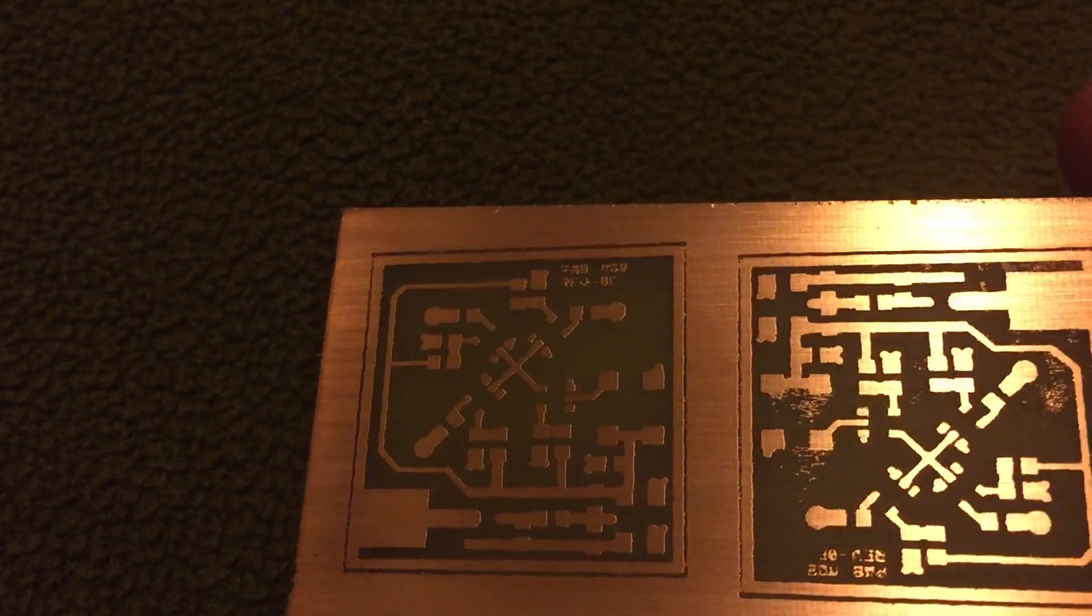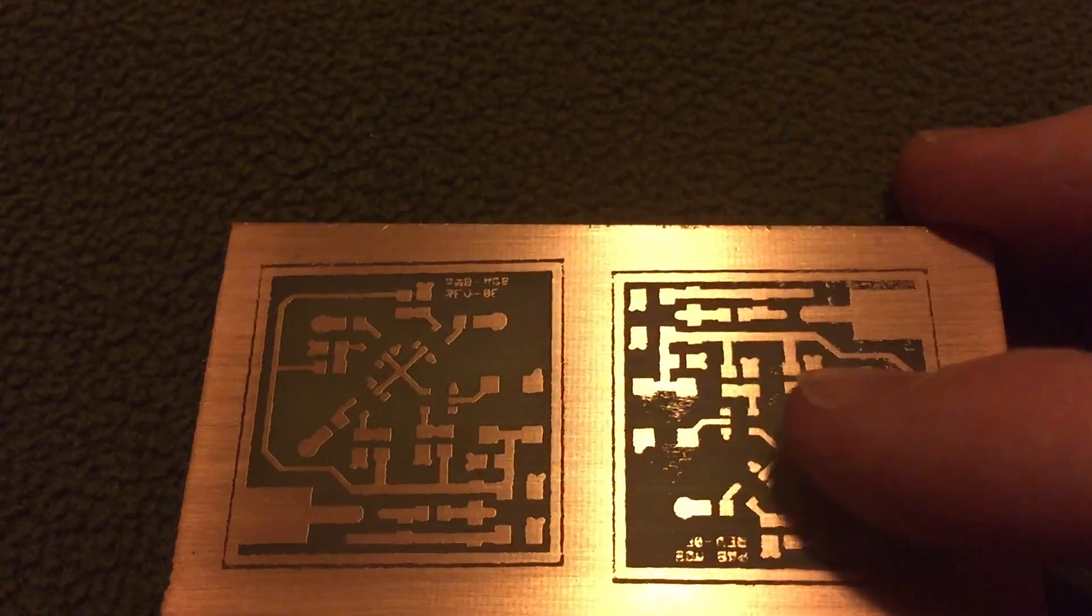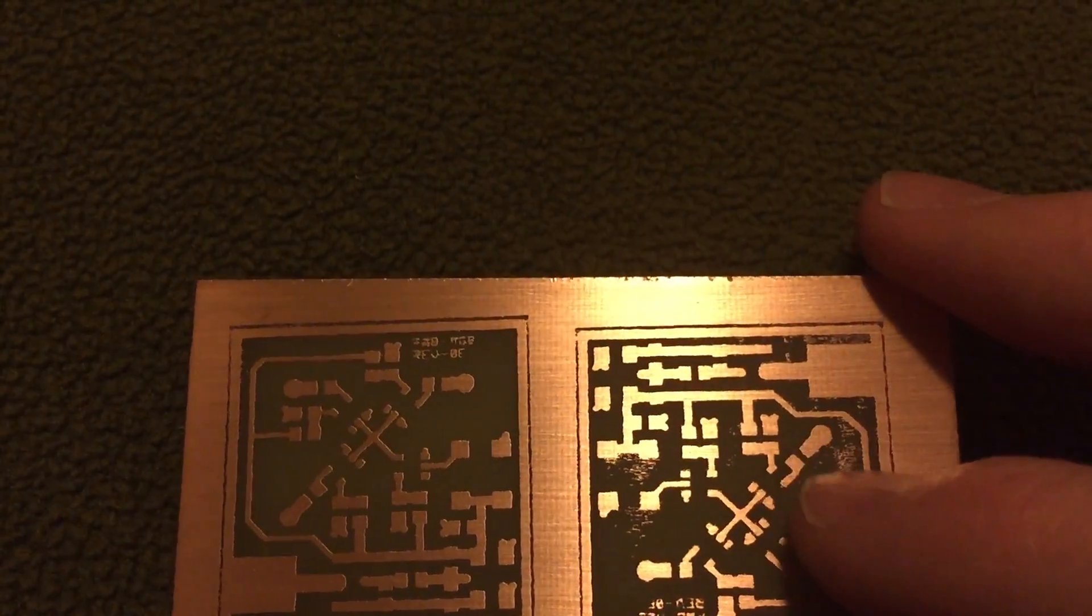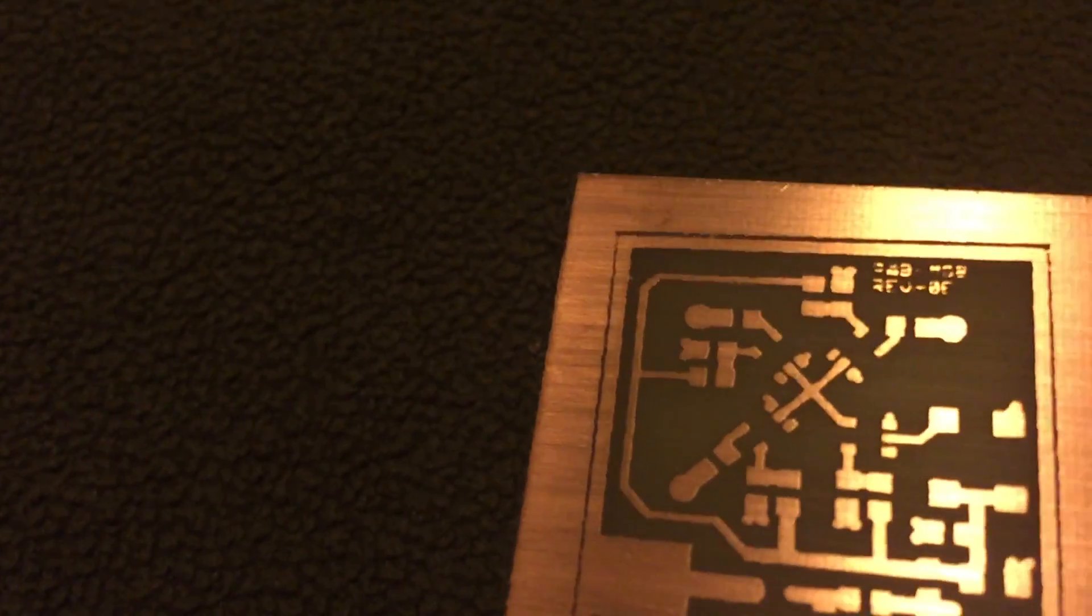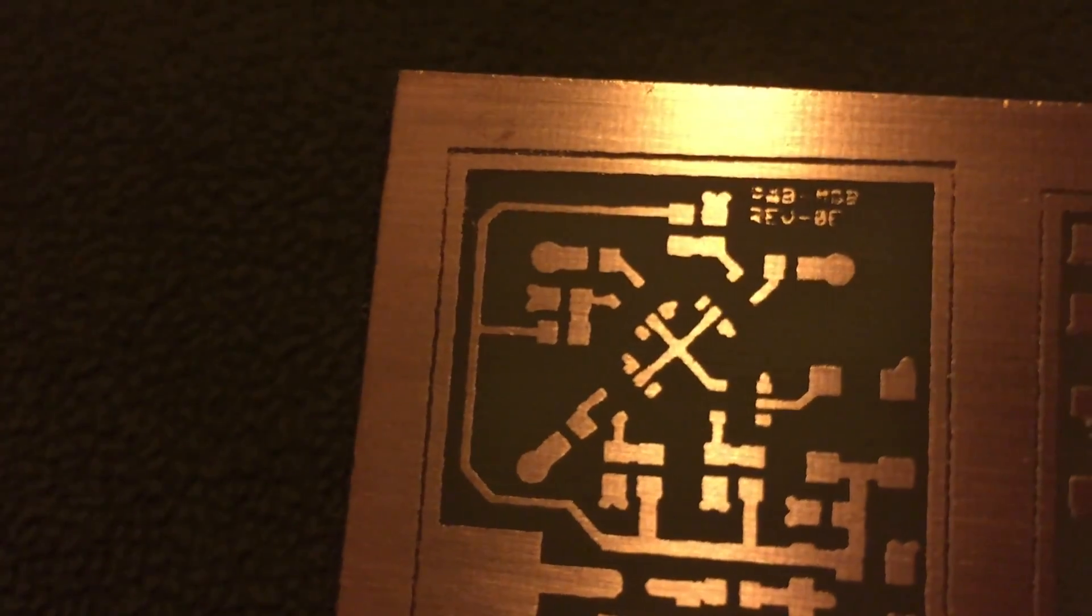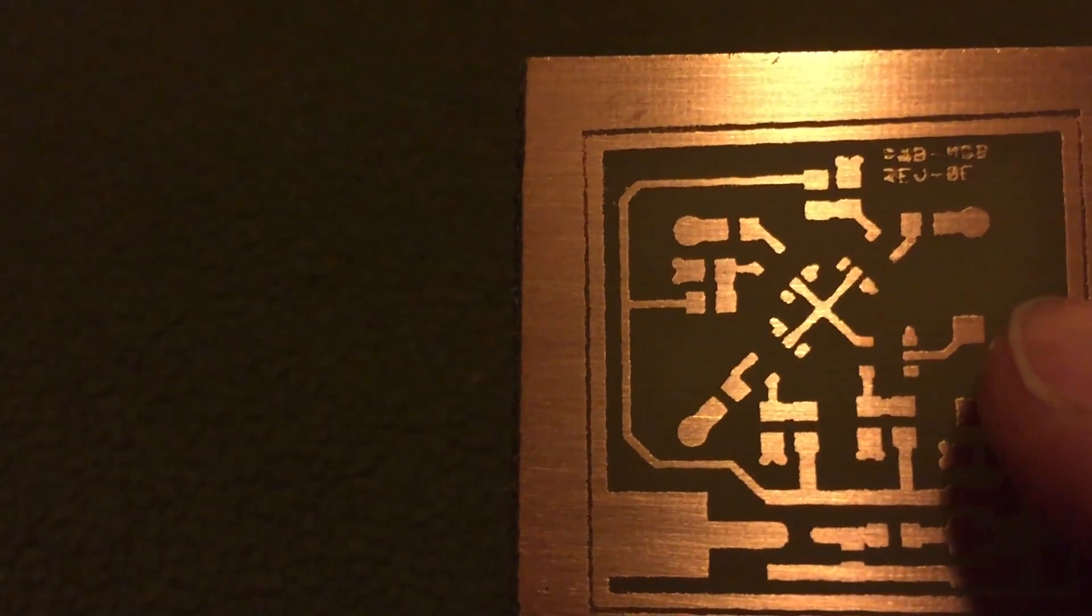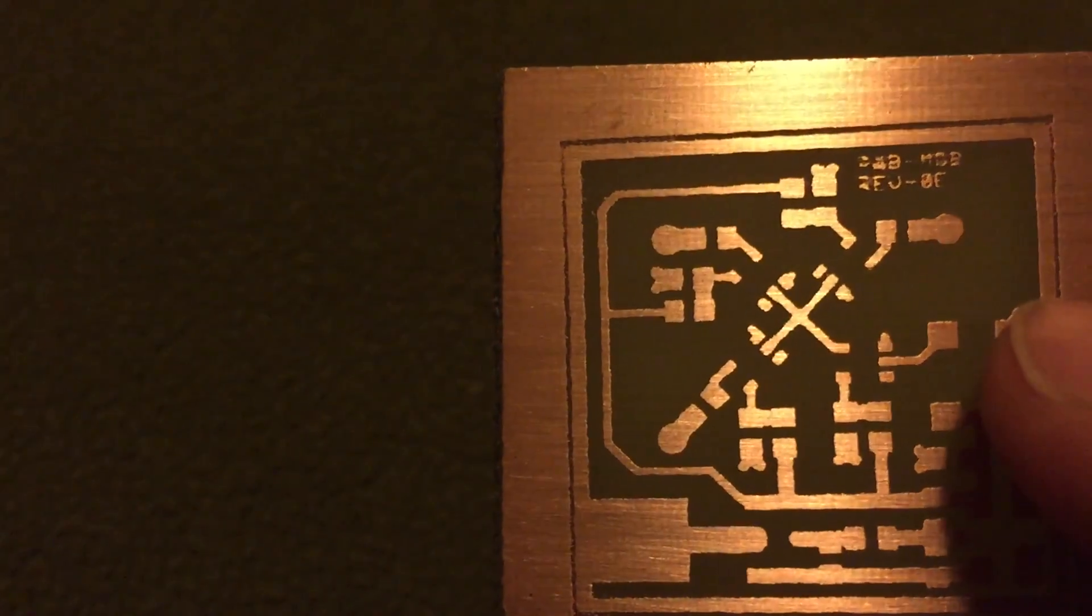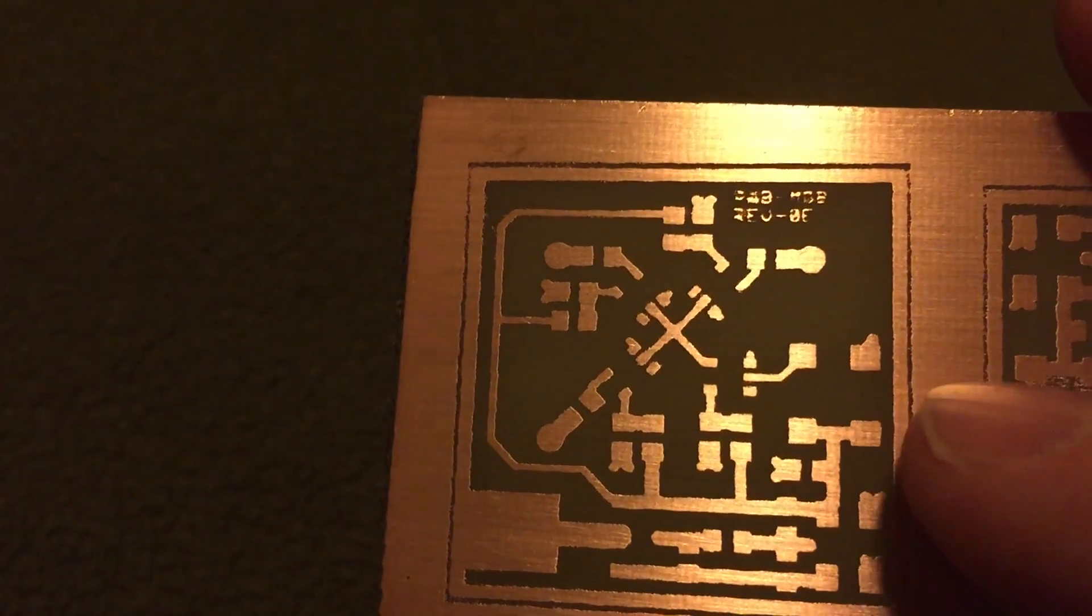I took it out of the etch and used acetone to take the paint off, then gave it a quick once over with the scotch-brite. This is the 100% speed side and you can see that it didn't quite get through the paint everywhere. This is the 50% side and it did a pretty good job getting through it all. There are a few spots where the etch isn't so great. You can see there's a little hint of copper between those pads. The text almost came out up there.